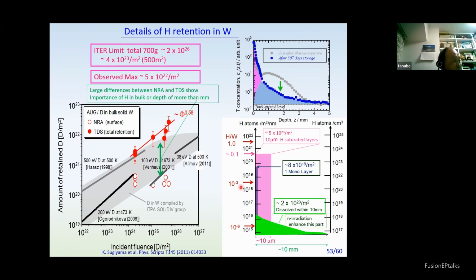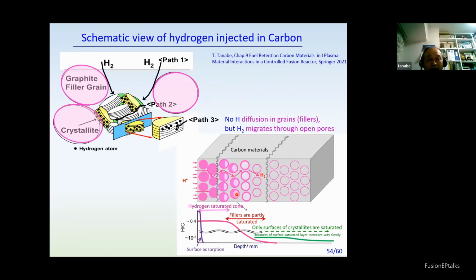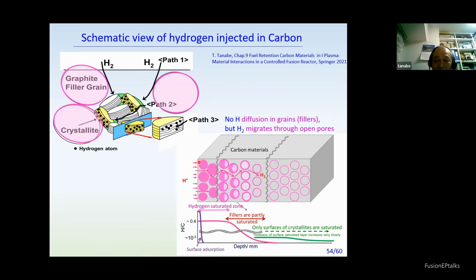This is the accumulation of hydrogen in tungsten. In the case of carbon, it has a very special structure - like a single crystal graphite, but defective, and hydrogen accumulates this way. Even under plasma exposure, the structure does not change; only the surface and bulk are saturated like this, with no diffusion in the fillers.